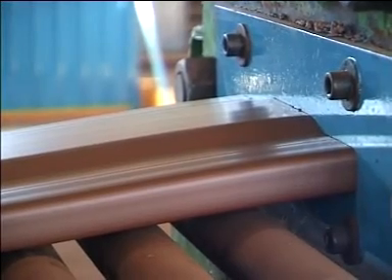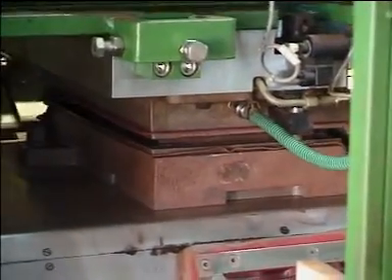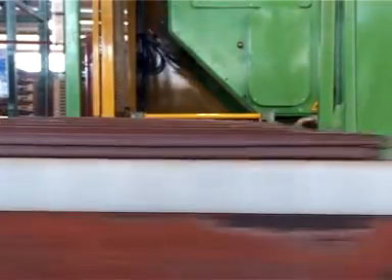Clay is fed into a de-airing mixer, where the air is removed by shearing the material through a vacuum chamber. The de-aired material is then extruded through a shaped mouthpiece at an enormous pressure, resulting in a formed strip of clay, which is then cut to size. Further forming takes place by precision pressing to mold the clay into the desired profile. It is then piled onto setters, prepared for drying.